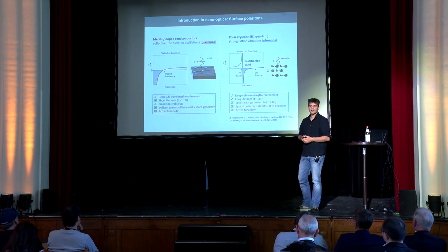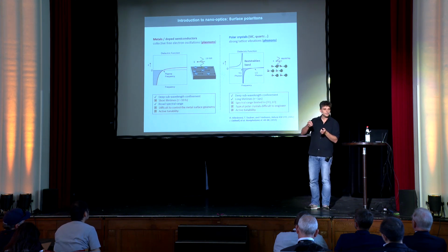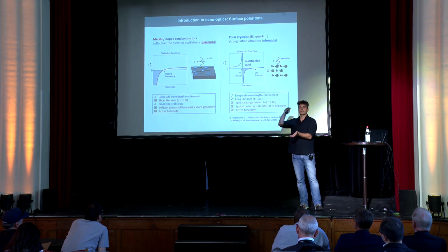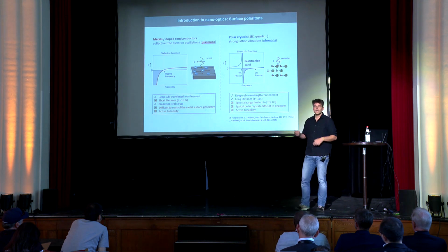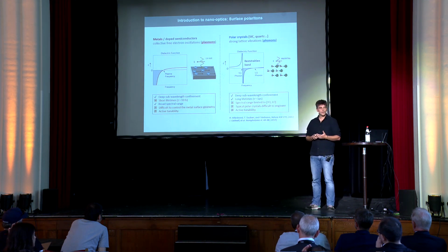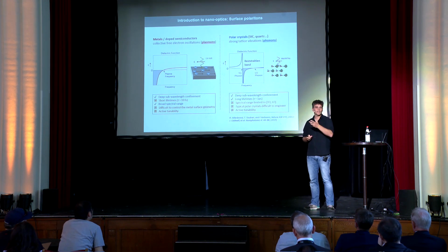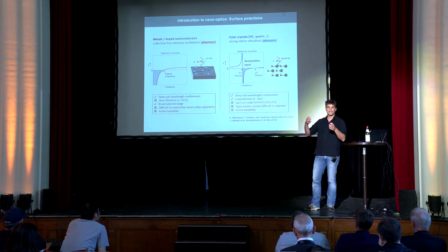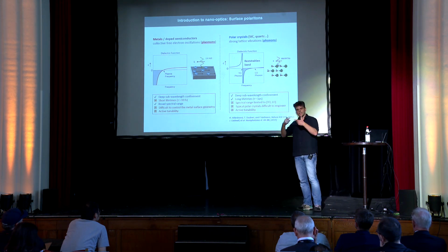Normally, in plasmons, it's the free electrons that react to the electric field, and then they create this movement that screens out the incident field and creates this surface wave. But we can also have polar crystals, normally biatomic crystals, where one of the atoms is more electronegative than the other, and therefore the electronic charge is more around one atom, and it creates a natural dipole in the lattice.